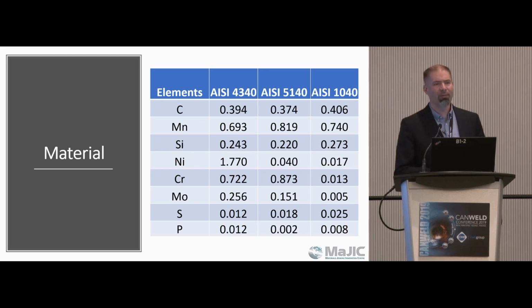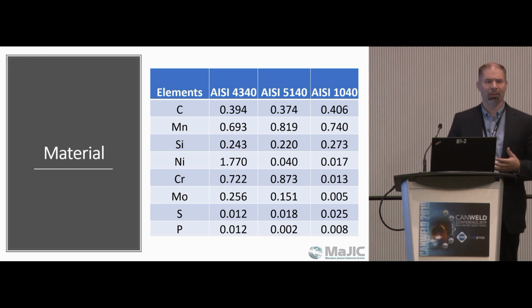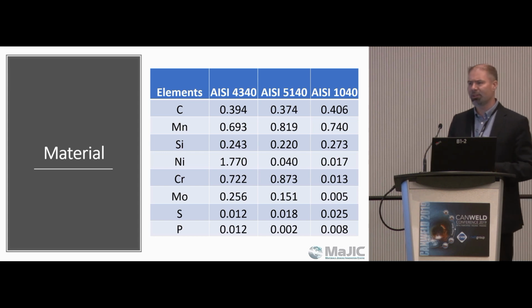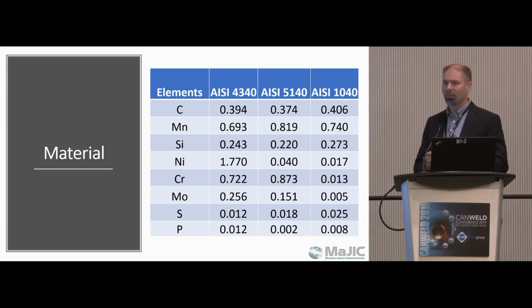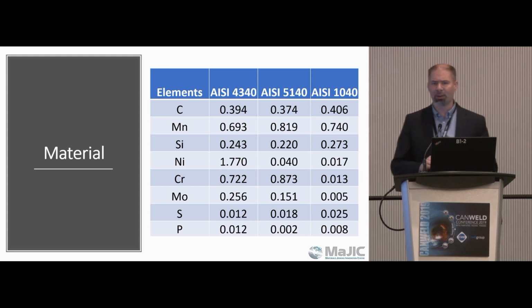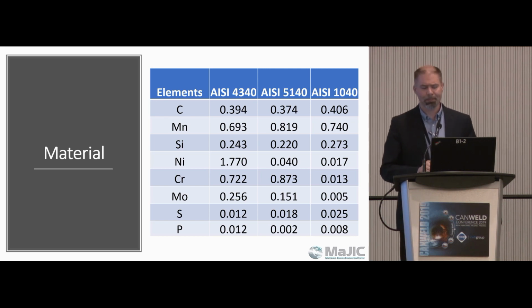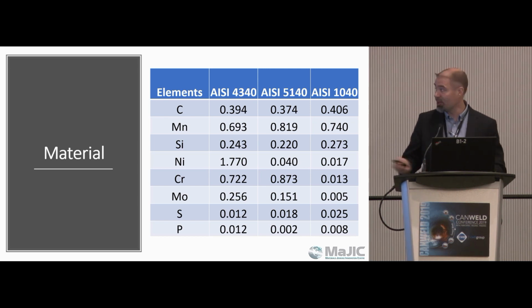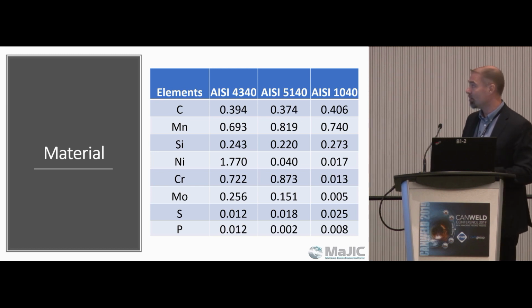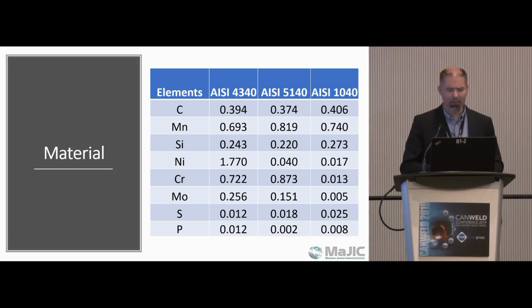4340, 5140, and 1040 steel. So 2 very hardenable steels and 1 mild steel or low alloy steel with lots of carbon. As you can see, the chemical compositions are all well within range. The carbon content is just hovering around that 0.4 mark.